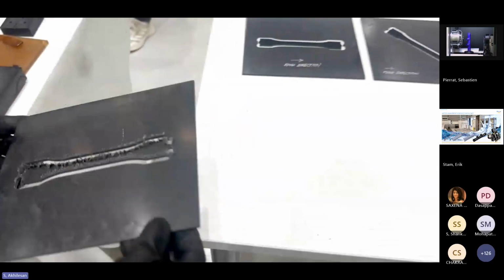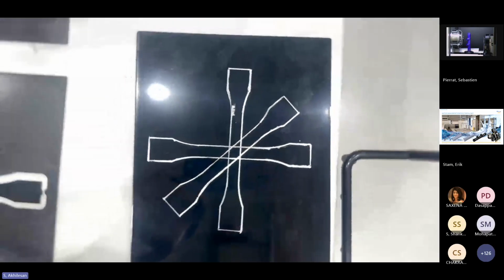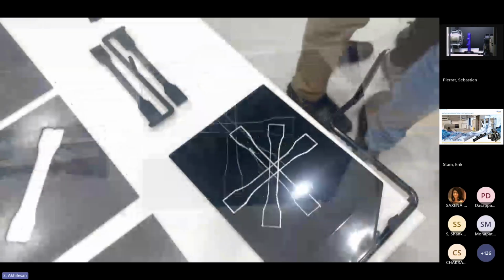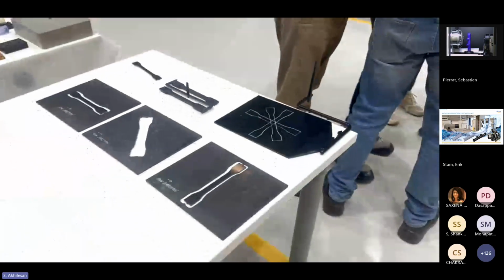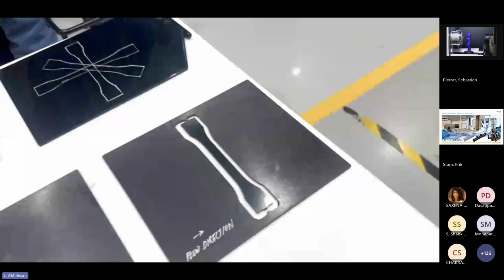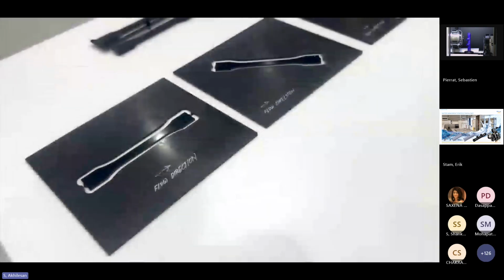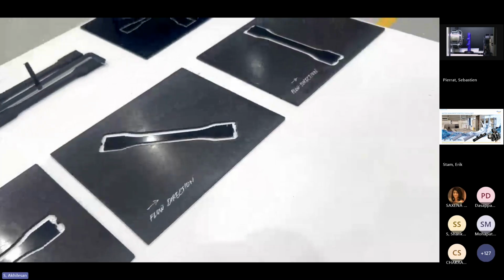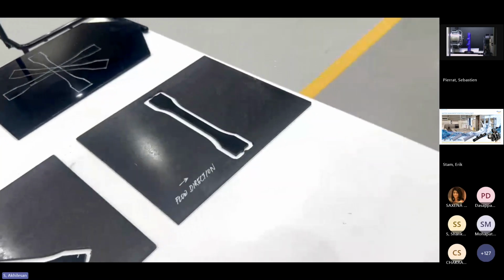or mill out specimens in 3 different directions typically. The 0 degree, which is in the direction of the flow, 90 degree, which is perpendicular to the flow, and at a 45 degree or a 30 degree, depending on the test. Once we have machined these specimens, we take them to testing.